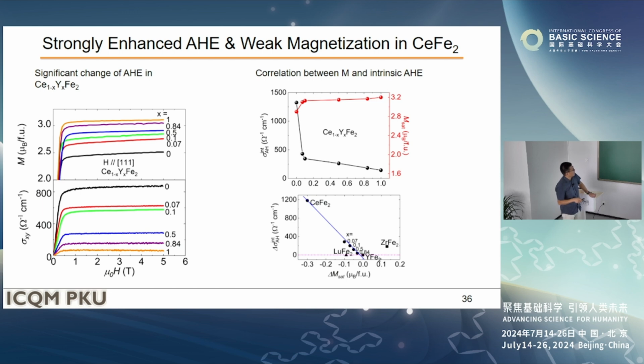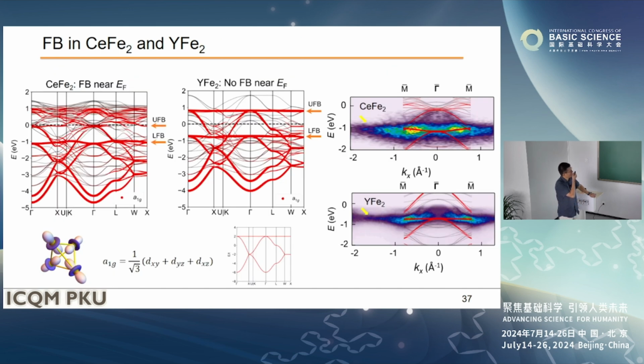We studied it in our way. We made some pseudo-alloy compounds of the cerium and yttrium iron. You notice these two compounds have a very small difference in saturation magnetization. But the anomalous effect of cerium is much higher. So with a very small amount of yttrium doping, you see a significant drop of the intrinsic anomalous effect. And then further, the magnetization increases slowly, and the anomalous effect decreases slowly as well. This part shows delta M versus delta anomalous conductivity. You see a closely linear shape. Very interesting. So how do we understand it?